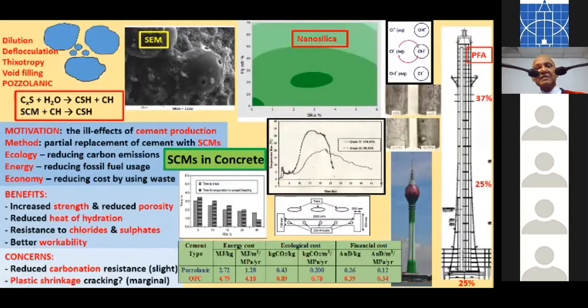Because there is less amount of cement, the susceptibility to chlorides and sulfates is reduced because the amount of cement is diluted. So one of the ways that chlorides are responsible in marine environments is the corrosion of the reinforcement. Normally there is a layer of concrete between the surface and the reinforcement, but the chlorides can get close to the reinforcement through this ion exchange process. So the chlorides exchange for an OH ion. But if you have fewer OH ions, as is the case with the fly ash mixes, then the rate of progress of these chloride ions is less. And also the porosity, like I said, is less. And therefore the chloride ingress becomes less for that reason as well. And so there is resistance to chlorides and sulfates.